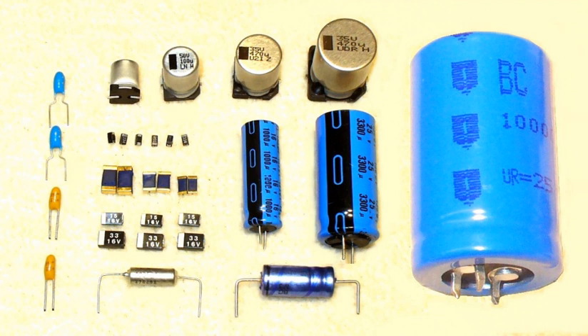For tantalum capacitors, a DC bias voltage of 1.1 to 1.5 volts for types with a rated voltage of 2.5 volts, or 2.1 to 2.5 volts for types with a rated voltage of greater than 2.5 volts, may be applied during the measurement to avoid reverse voltage. The capacitance value measured at the frequency of 1 kHz is about 10% less than the 100/120 Hz value. Therefore, the capacitance values of electrolytic capacitors are not directly comparable and differ from those of film capacitors or ceramic capacitors, whose capacitance is measured at 1 kHz or higher.